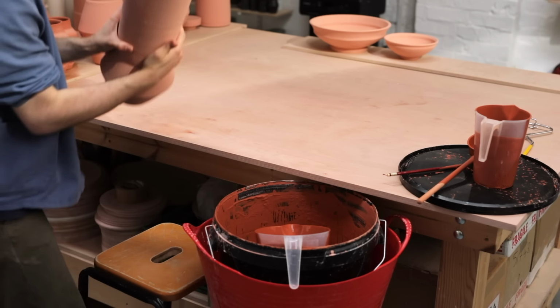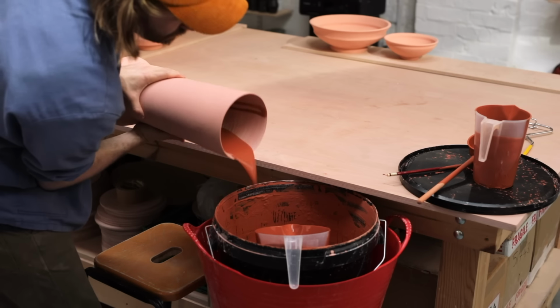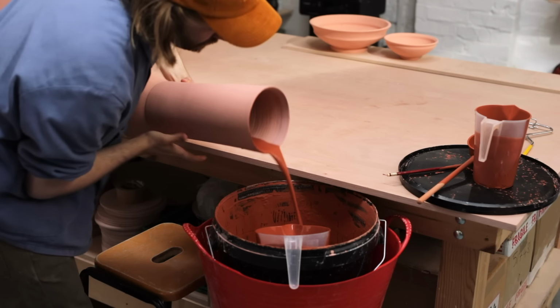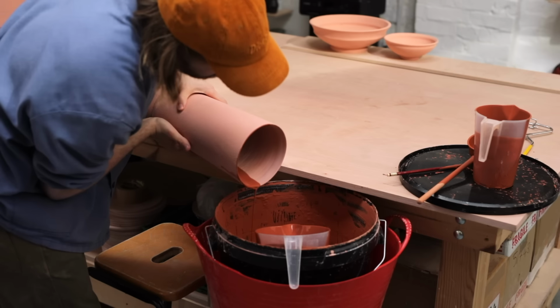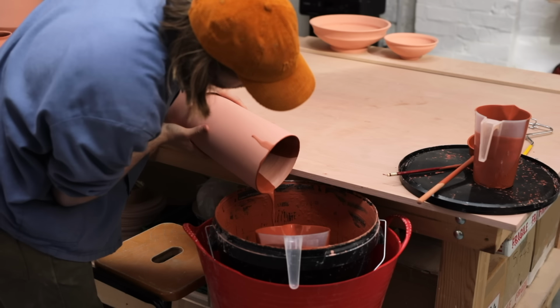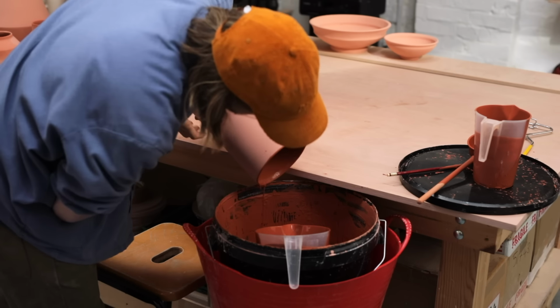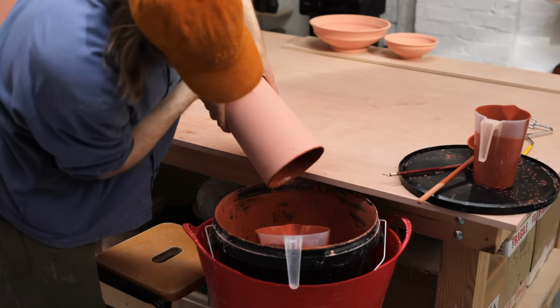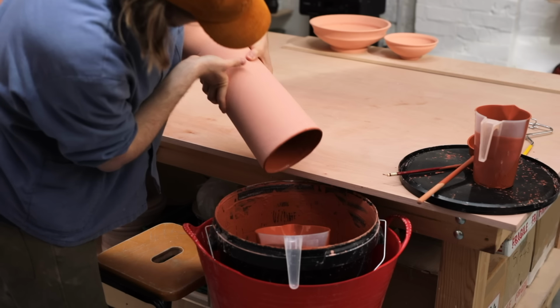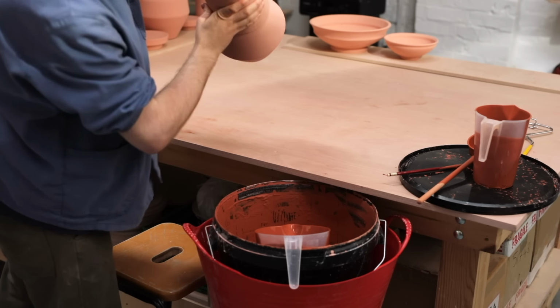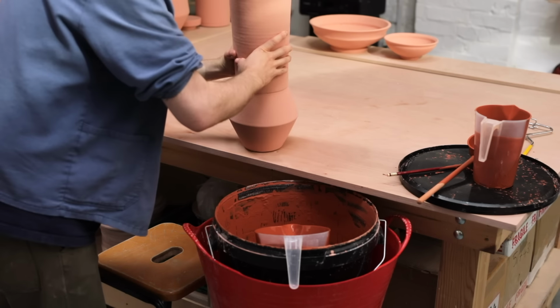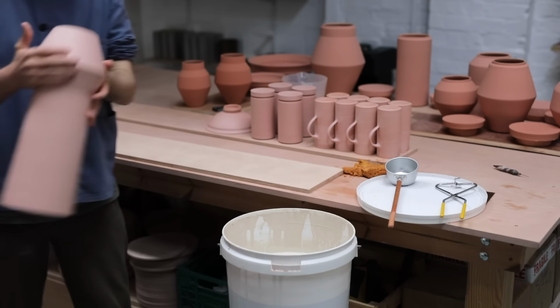I then pick the pot up, which is filled with glaze, and I carefully pour it out, rotating it as I go so the glaze can coat all the surfaces. And whilst this did work, for this dark green variant I don't think I put enough glaze in initially, as once fired the glaze on the inside was thinner than I'd usually like. This next glaze I'm using is exactly the same as the previous one, it just lacks the red iron oxide.